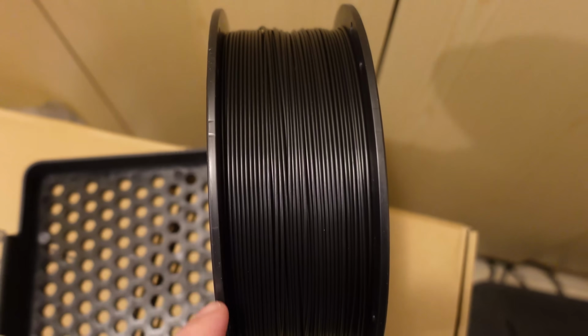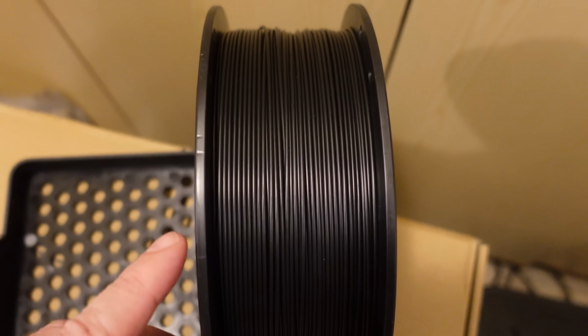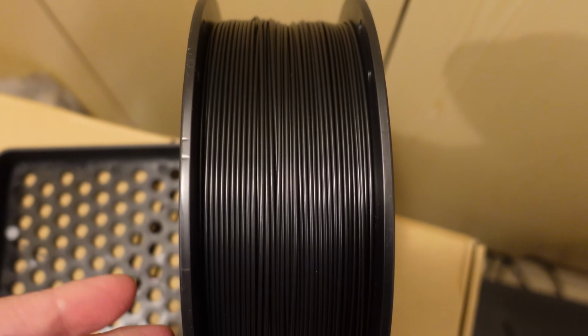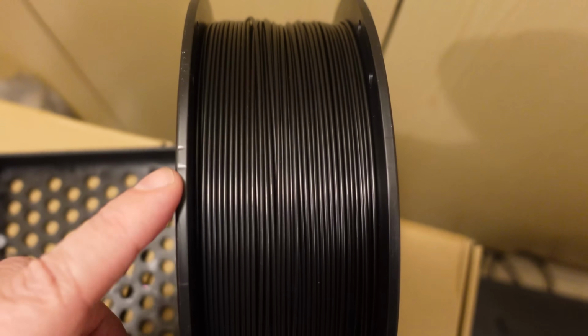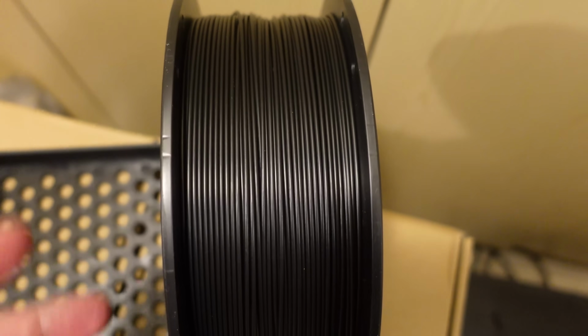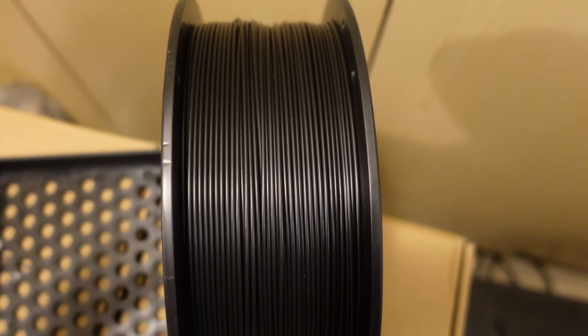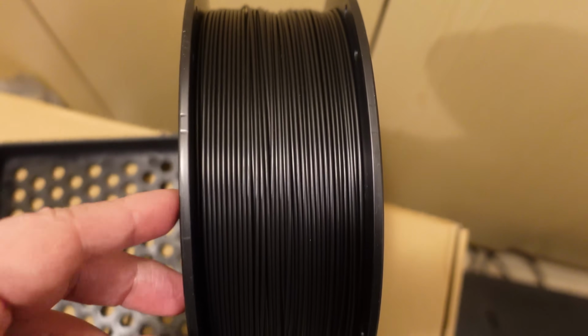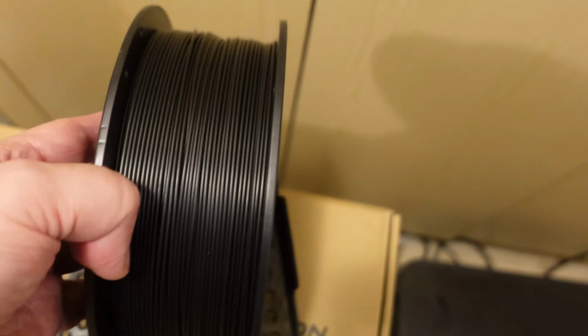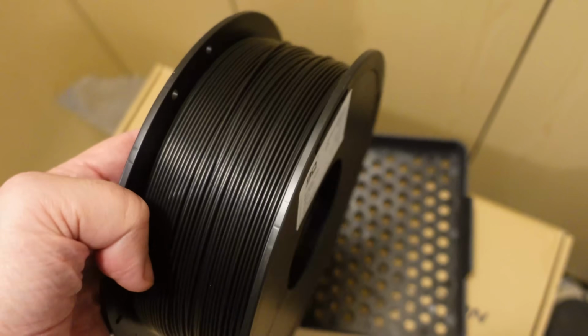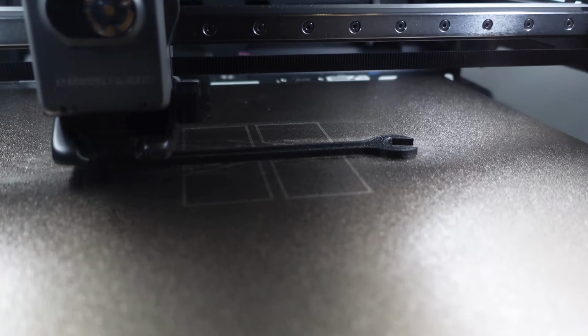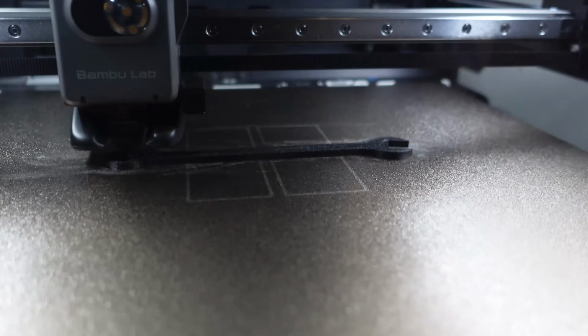It is still hot, I cannot touch it. I started with 96 degrees Celsius measured and I rotated the spool every 15 minutes, and I noticed that it started to be damaged, so I reduced the temperature to approximately 87 degrees Celsius measured. After 6 hours, if this does not help, then I don't know, nothing will. Soon it will be finished and I'm still not sure if it is better or not.